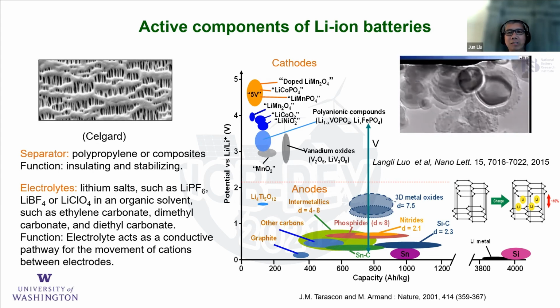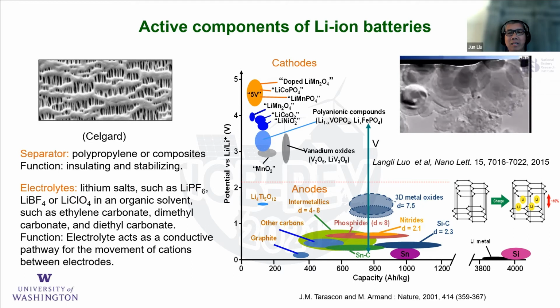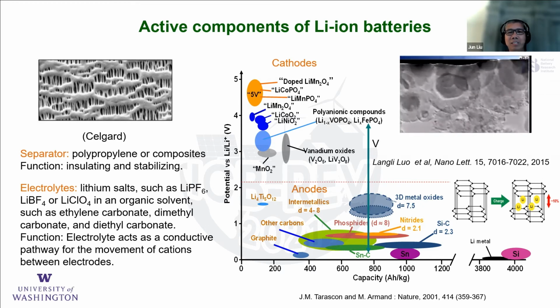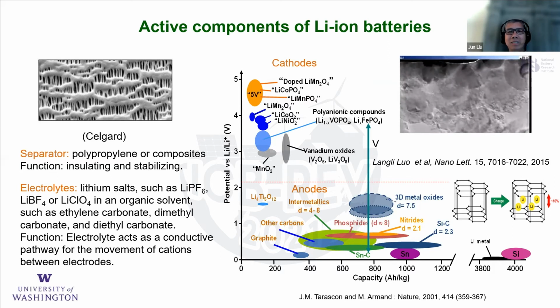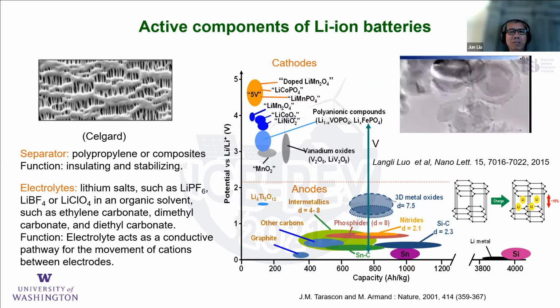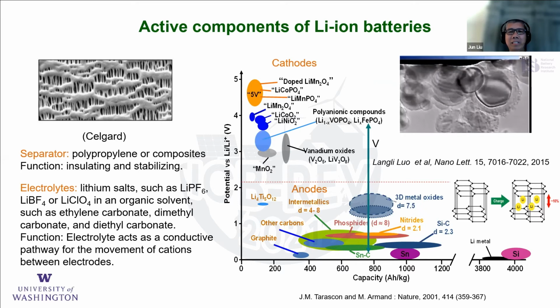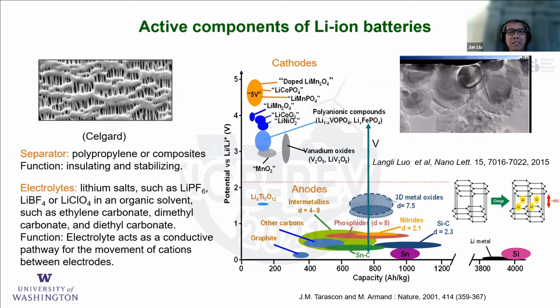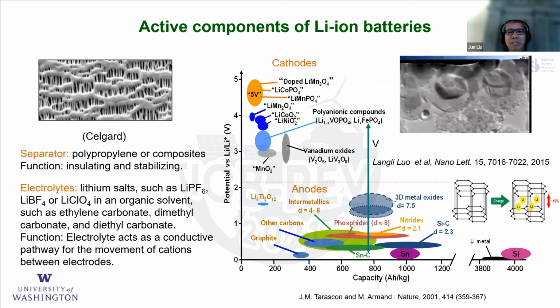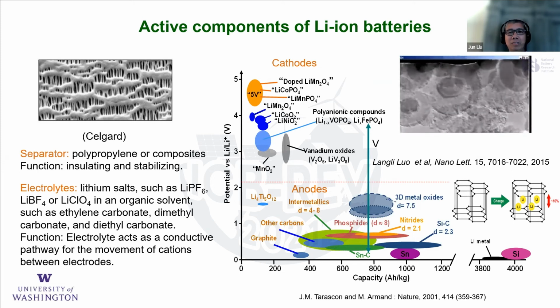The candidates for those include silicon, for example. Silicon has 10 times more capacity, but the volumetric expansion is huge. It's more than 300%, as shown in the TEM here. When you charge it, it essentially, like a brace, bends and shrinks. Therefore, it's very difficult to stabilize. However, great progress has been made, and silicon is on the way to being commercialized. Another important option, probably the most important one today, the holy grail, is to use lithium metal as the anode material.